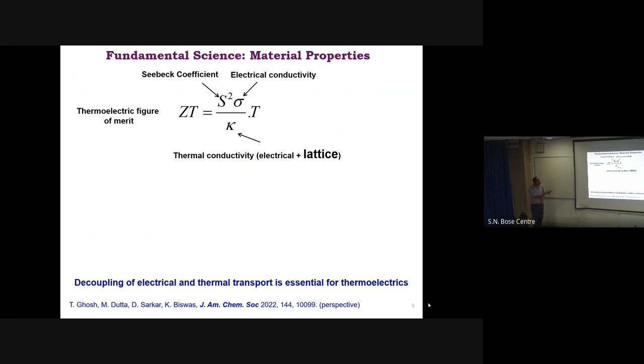And we know what electrical conductivity is: how fast charge carriers can move from one end of a material to the other end. So the numerator has only electrical transport, whereas the denominator is the thermal transport. Thermal conductivity has two parts. The first is the electrical part, where charge carriers carry the heat, which is directly related to the electrical conductivity by the Wiedemann-Franz law. So we don't have much control over the electrical part, because we need high electrical conductivity but low thermal conductivity. This part we generally don't touch because that is not in our hands.